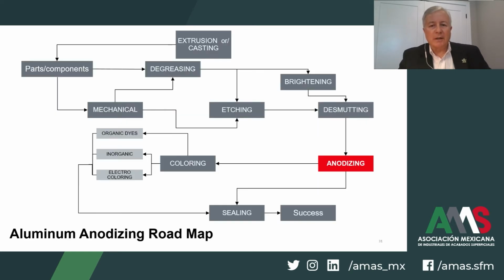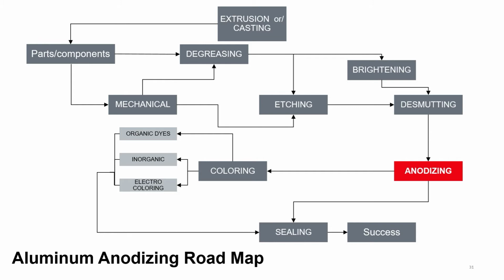Here is a roadmap for the anodizing process for aluminum. Considering cast versus wrought alloys, the etching chemistry, as I said, is very important and critical, and we must have a different approach or a special type of etch chemistry. For cast alloys, using an acid conditioning and brightening with acid etching is very important, while trying to avoid using traditional caustic etches, which create complex smuts on the surface. The desmutting chemistry also must be sufficient and designed to remove the complex smuts of copper and silicon. Without doing this properly, the anodic oxide will not be formed properly, and we will have inhibited surface thickness, which causes all kinds of different problems. That will be discussed more in the webinar.